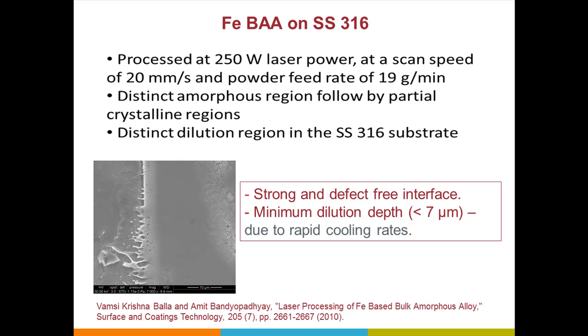This is the result on stainless steel, and again we published this one. We see the actual dilution zone is only 7 micron, meaning only 7 micron where bulk amorphous alloy chemistry and the stainless steel chemistry is mixed. So pretty much we can preserve the bulk amorphous alloy coating layer very nicely in the coated samples. That's not a problem at all.